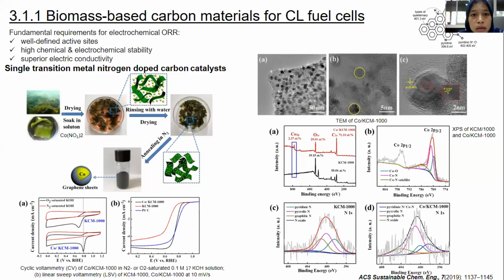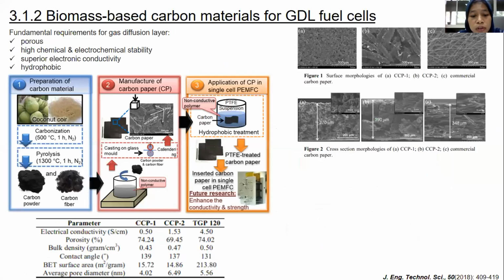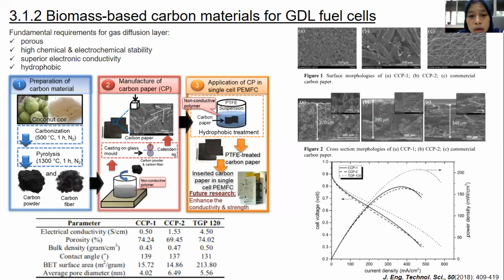Okay, this is the application of biomass for GDL. This is our research also. We successfully produced the GDL from coconut fiber at a temperature of 1,300 degrees Celsius. And we were also successful in testing this composite in the single cell of a fuel cell, and its performance compared to the commercial carbon paper.